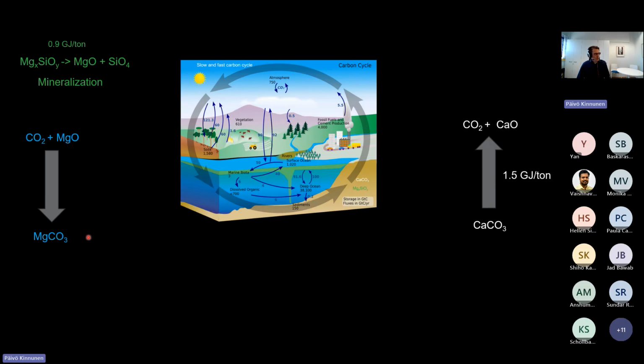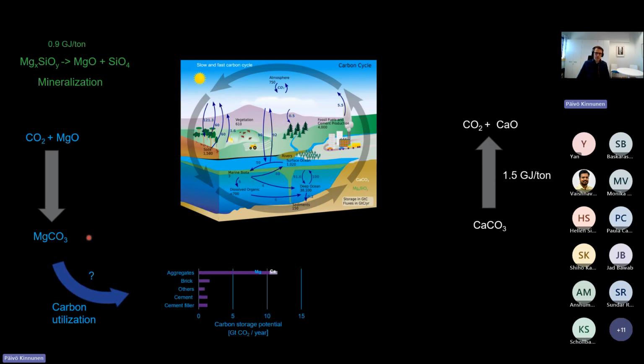And so the next step, if we think straightforwardly, is that, okay, if we first mineralize it, so maybe a little bit of background, I will go more into detail in the mineralization, but here it's just mentioning this is mineralization, and if we want to then utilize it, this is a powder. This magnesium carbonate is a really fine powder. It's pretty much like dust. The particle size is about 1 micron. So it's a really difficult material to work with. And the main question then, if you want to utilize it, is how do you increase the particle size, or how do you bind it together, basically?